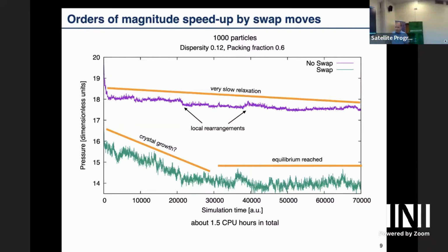It turns out when you start at the beginning, the pressure is pretty high because the particles are pretty jammed together and they're pretty unhappy. And as you go on, the particles make more space for themselves, so they get more ordered, and then the pressure drops. And pressure, in all of these simulations, is a pretty good indicator for the progress of ordering or of relaxation. So you see here for no swap in purple, there's a pretty sharp drop, and then it goes down pretty slowly. This is at 60%, so pretty high density, 12% dispersity, so that's well above the barrier where we see ordering.